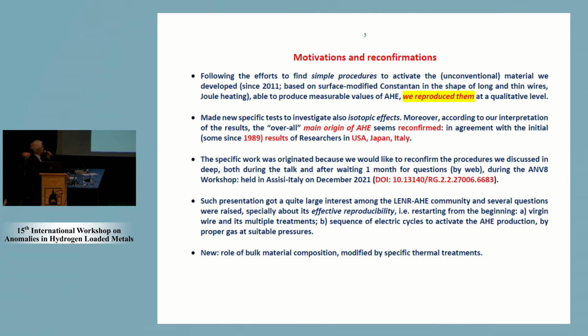The motivation was to reproduce the anomalous effect in a simple way. We have done a lot of work using pulse. We demonstrate that a pulse condition is able to promote fast loading of the material and the effect, but it's really difficult, and not useful for common people, for normal students, or industry. So we have found that applying DC current for a very long time at high temperature is equivalent to pulsing for a short time. It means 5 hours in pulsing is equivalent more or less to 10 days in DC condition. Just to have an idea.